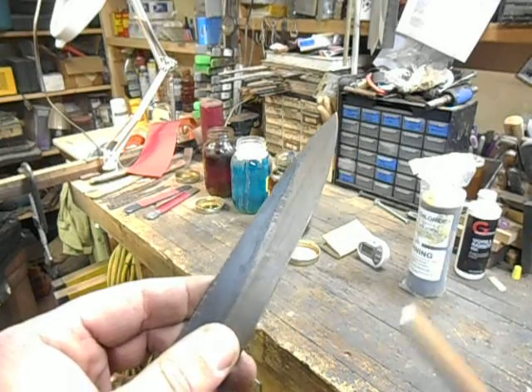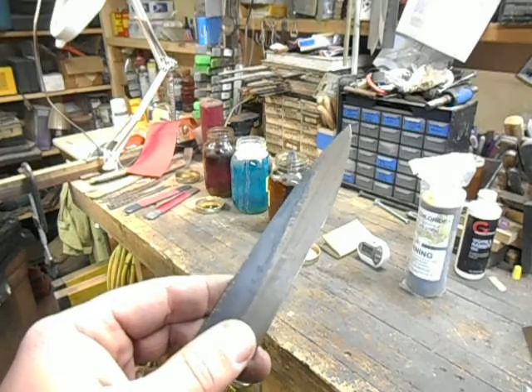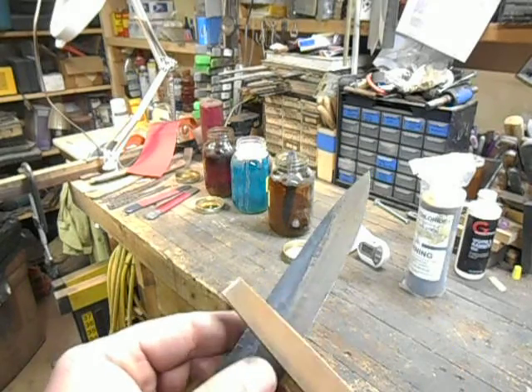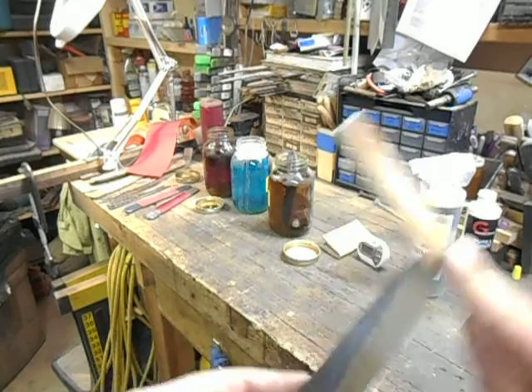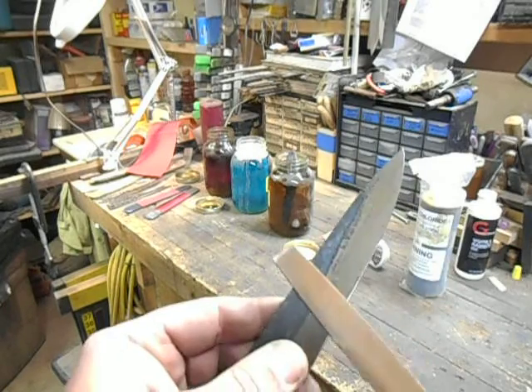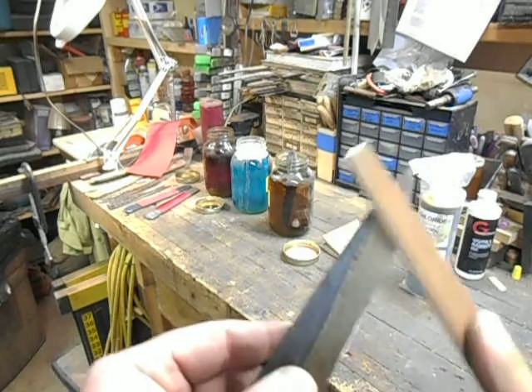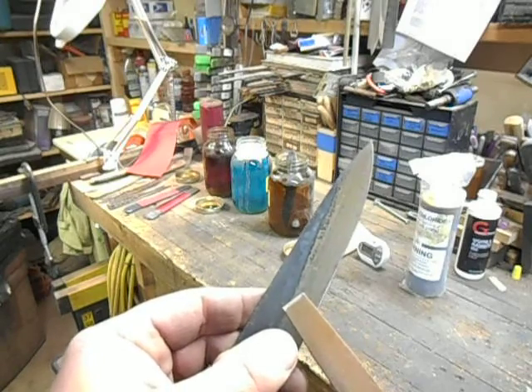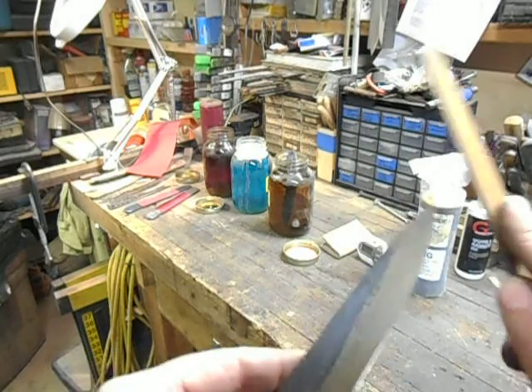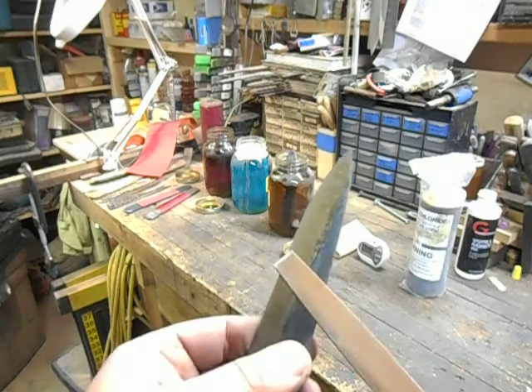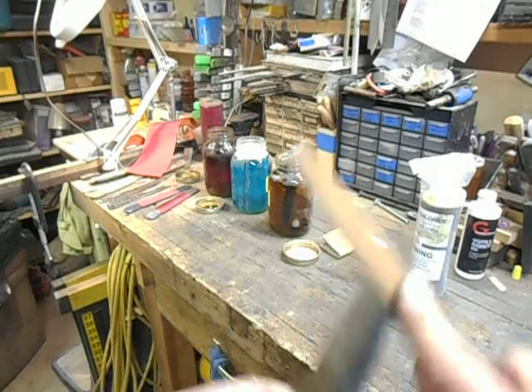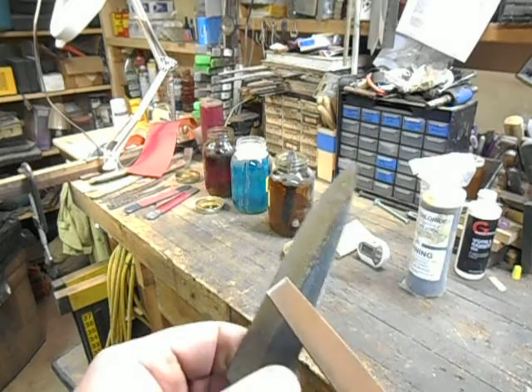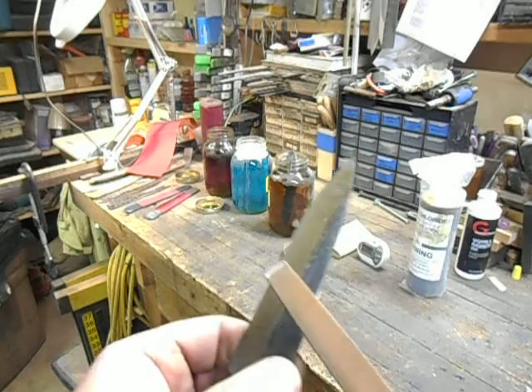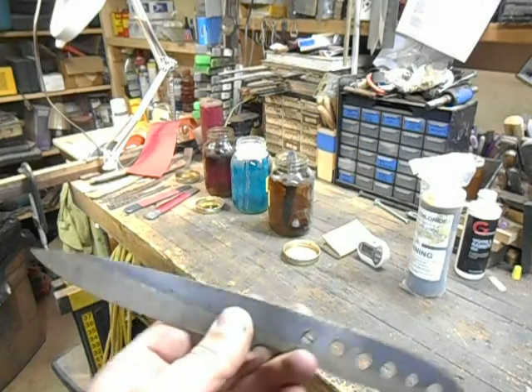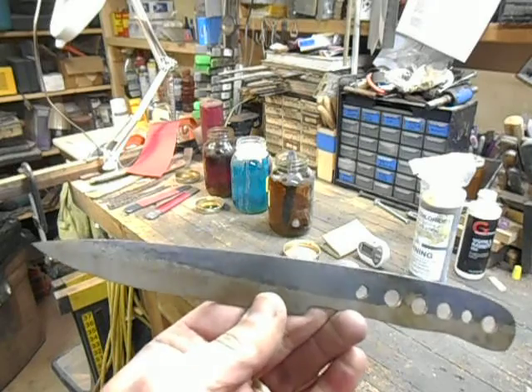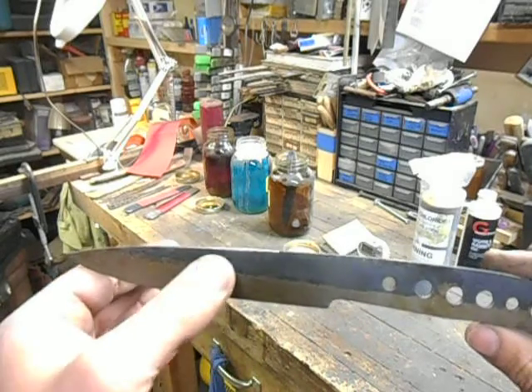lost carbon because it was exposed to the heat from, in this case, the kiln. So usually you'll have a couple of strokes where the file will kind of bite and kind of not, and then as soon as you get past that first couple of strokes, you'll get that skating sound where the file's not cutting it. Now if you go to the spine, there's a completely different sound. There's no ring, and I can feel that file biting in there. Okay, so that right there is a check of your heat treat, just your scale patterns.